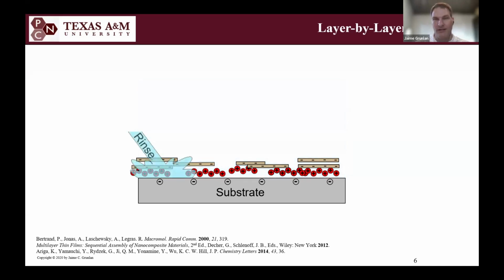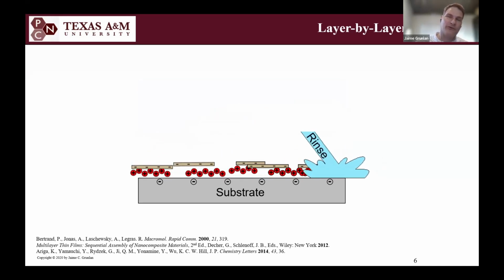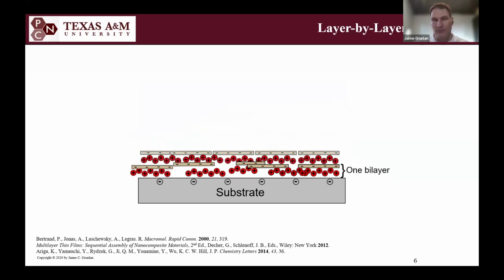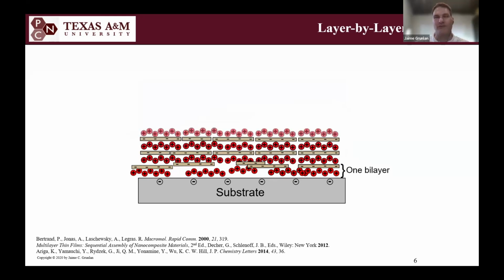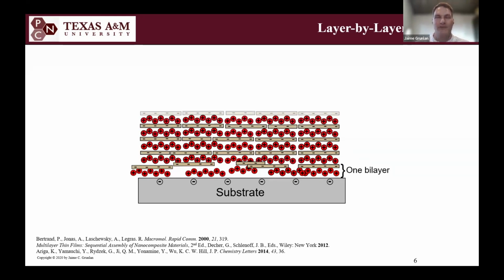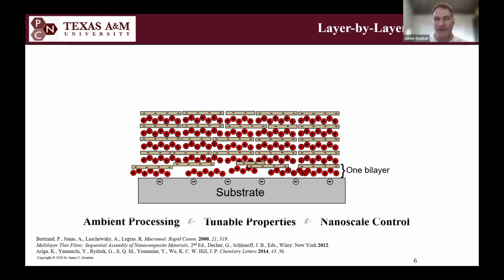You're seeing it on the screen there, this cartoon, where I'm exposing a substrate to cationic and anionic nanoparticles and/or polymers. And this is just one example. This cartoon you're seeing here is supposed to be some kind of cationic polymer and anionic clay nanoplatelets. I call it a nano brick wall. We've done a lot of work on the nano brick wall kind of structure. But the beauty of this technique is its self-limiting thickness of layers, and all the processing is done under ambient conditions, and you can truly tailor just about everything in these kinds of thin films.